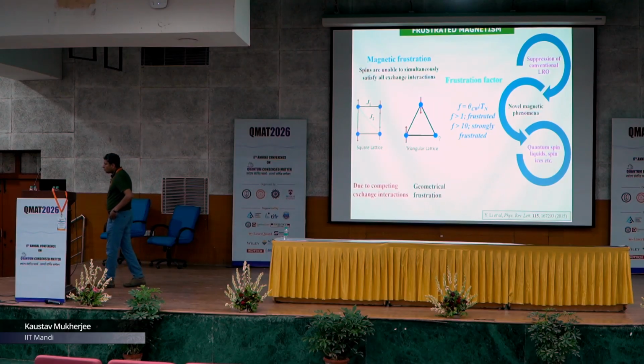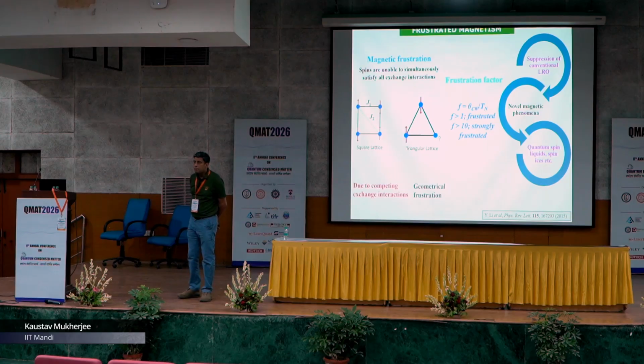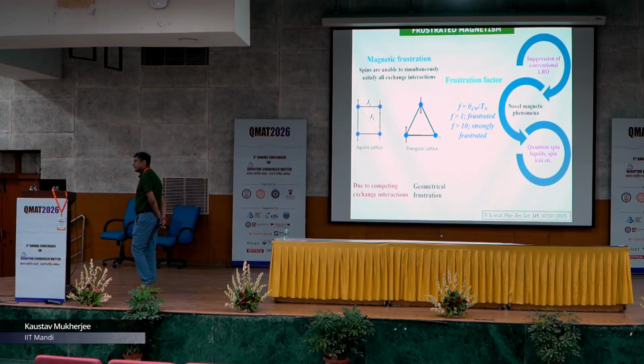Now, to quantify this frustration, a frustration factor was introduced, which is nothing but the ratio of the Curie-Weiss temperature and the magnetic ordering temperature. The Curie-Weiss temperature, as we all know, can be obtained by fitting the inverse susceptibility versus temperature curve with a Curie-Weiss law, and we can get theta CW, and TN is the ordering temperature. Now, generally in literature, if f is greater than 1, a system is said to have some frustration, but for the condition when f is much greater than 10, the system is said to be strongly frustrated.